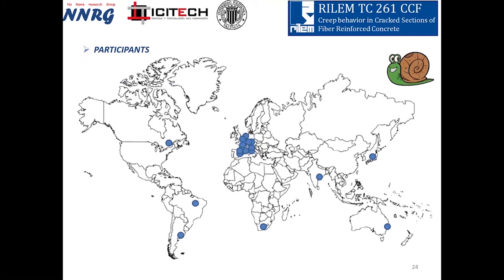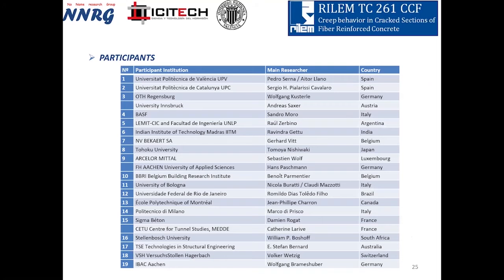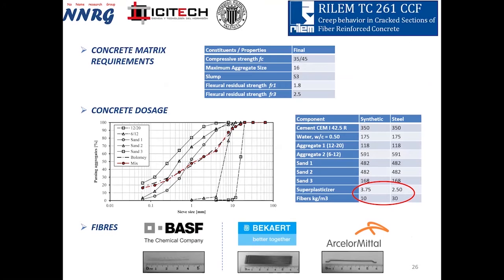Okay. Then for the round-robin test, we have a good response. 19 laboratories everywhere in the world agreed to contribute. And this is the list of all the participants in the round-robin test that also, of course, participate in all the activities of the technical committee. The idea was to produce only normal strength concrete, 35-45 megapascals in compressive strength, with two variables only.